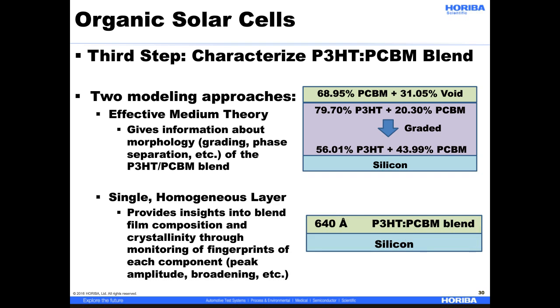The other way that we can characterize this is as a single homogeneous layer, and this can provide insights into blend film composition and crystallinity. Again, we're looking at those fingerprints for P3HT and PCBM, so we're interested potentially in the peak amplitude, the broadening, and some other things there.